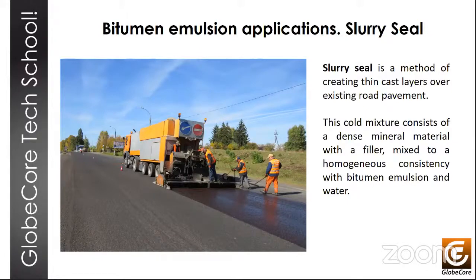When increasing thickness to improve mechanical properties and shear stability, latex modifiers are applied. The mixture has high surface tension and is self-leveling. With slurry seal, slight rutting and longitudinal deformations of the profile can be compensated and repaired. Since there are practically no voids in the hardened mass, it resists compression really well under traffic. After the coating is done, traffic can be resumed after about 1 to 4 hours.